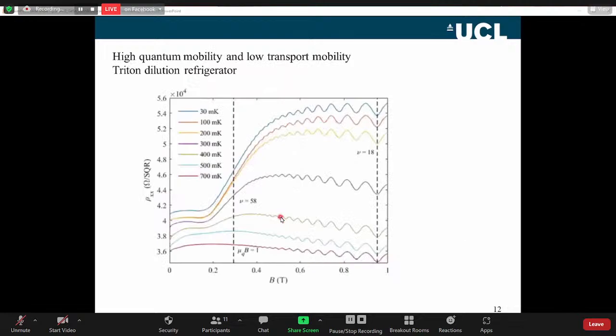We also cooled the system down further to investigate what happens at lower temperatures. We have a system called the Triton dilution refrigerator that goes down to 30 millikelvin. So we start at 700 millikelvin. Data here at 700 millikelvin. Again, as we cool down, we've got this very, very strong temperature dependence.